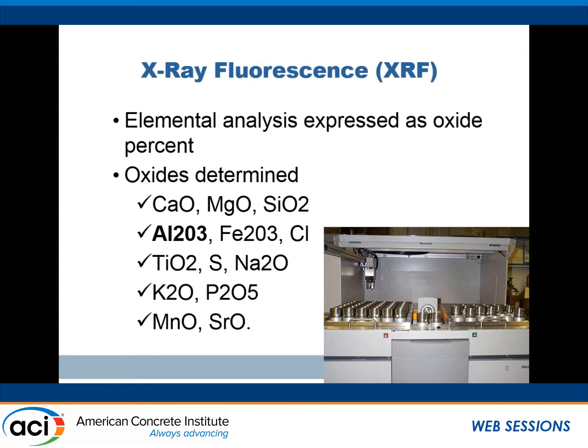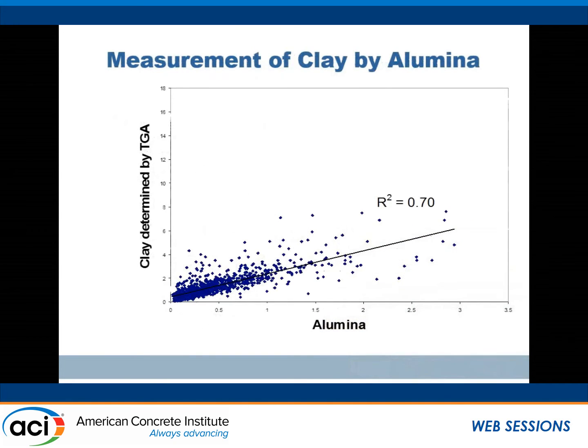So the first parameter that they're really excited about: alumina. Why? Because all clays contain alumina. So you can run an XRF and pick up what is the alumina content of the material. And I think that's the basis of what you were talking about, Heather, is if you're going to characterize an aggregate at its point of delivery, that ties in quite nicely with what we're doing here. So again, pretty simple stuff.